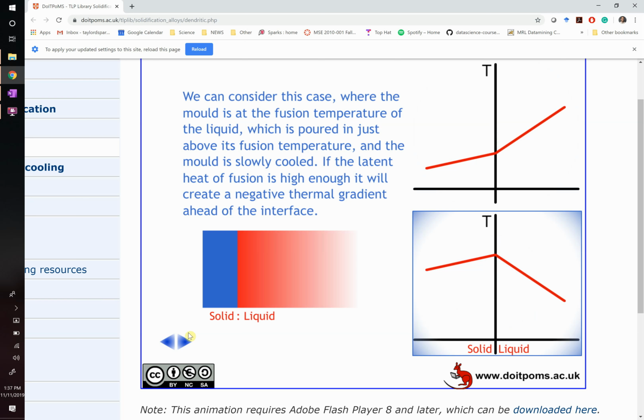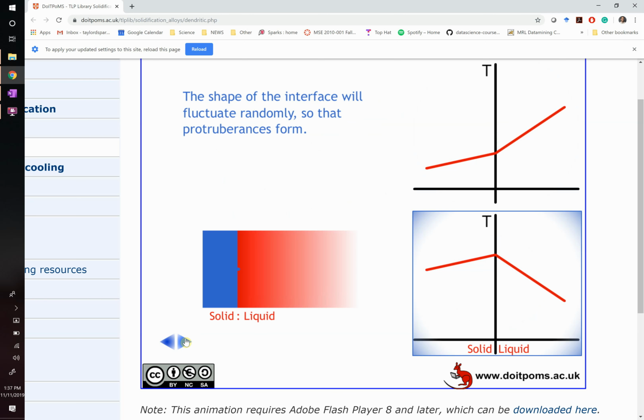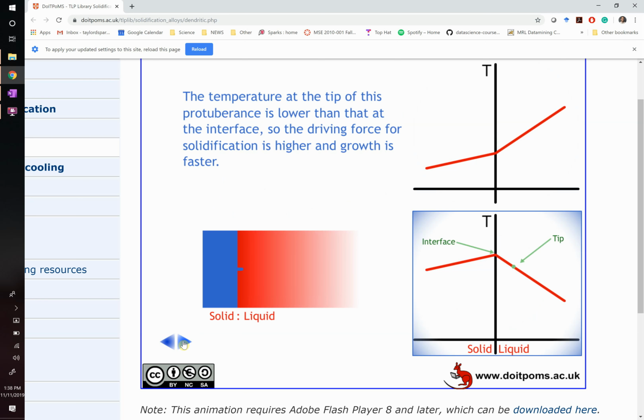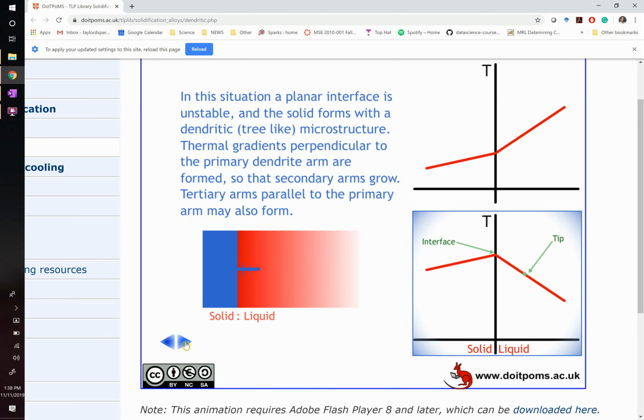So now think what happens. As a protuberance forms, a little piece of solid forms because of slight temperature fluctuations. As that thing forms, it's extending out into the liquid, which is going down in temperature. So it's not going to melt again. Instead, it's going to be stable. This is a stable imperfection. This is the start of the dendrite. And as it grows, the same thing happens off of the sides of it. They're going to extend outwards where it's slightly cooler, so they're going to keep on growing. And so you end up with these dendritic structures that grow through your material, right?